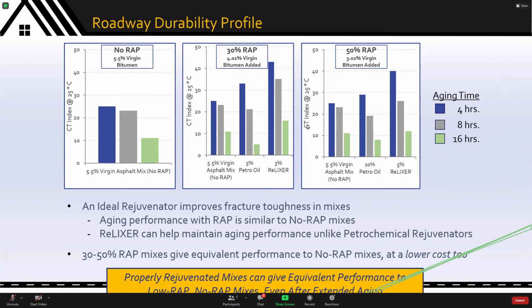That is not the case with ReLIXER. For both the 30% RAP mix as well as for the 50% RAP mix, you can see that it provides equivalent long-term performance. And I use this graph to highlight that with the right rejuvenator, with the right mix design, with the right dosage selection, it is possible to engineer roads with long-term performance, with high RAP, that show long-term performance that's similar to mixes with no RAP or low RAP.